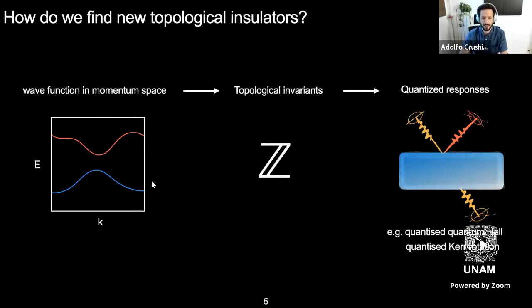Now, this topological invariant sounds a bit mysterious, but it is a way of extracting information from the wave function of a material. You take some integral that involves all k momenta, and you get a number. And this is kind of generically what a topological invariant is. And the claim is that this number won't change so long as you're in a given topological phase. And that's what makes it robust, and that's what gives it the name of topological insulators. And what's physically important is that these invariants tell you that certain responses, for example, if you shine light or you measure some transverse current, will be quantized in units of fundamental constants.